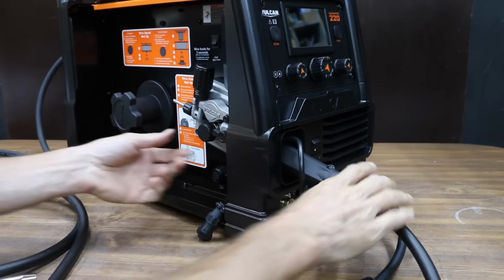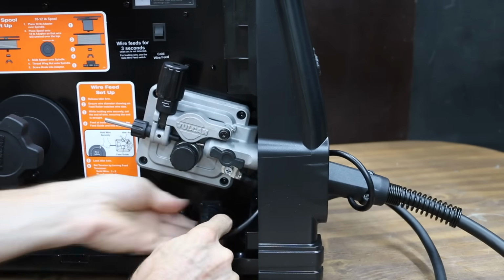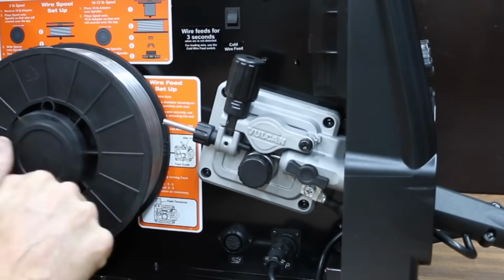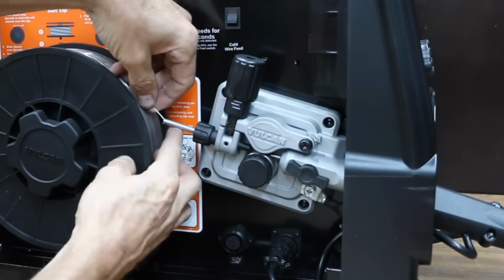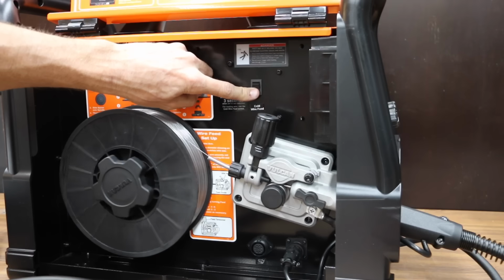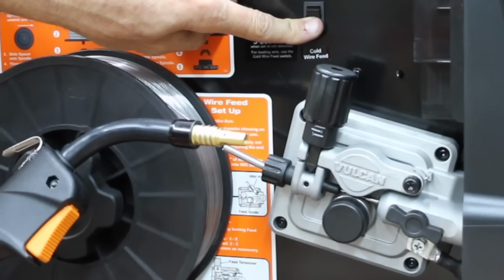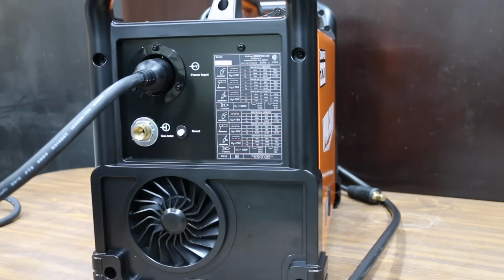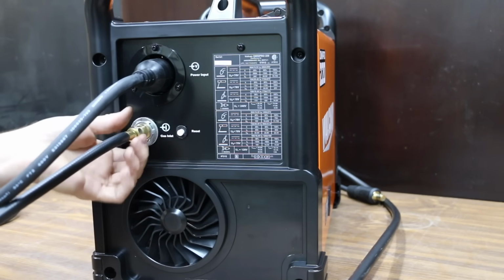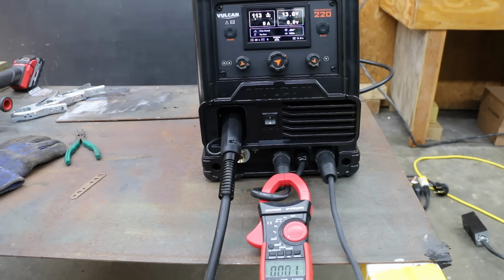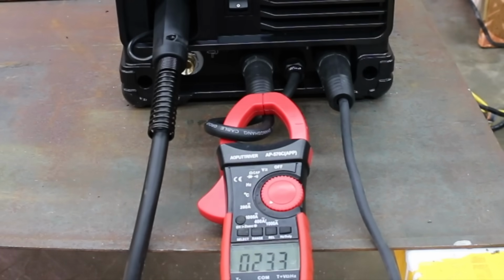Of all the welders so far, the Vulcan is by far the easiest for installing a roll of wire. However, it is a pretty large welder. The geometry for the wire feed is excellent and allows for a pretty straight wire run into the wire feed mechanism. There's a wire feed button to make the process even easier, and the gas supply hose has a threaded fitting. And with 10 pounds of wire, the Vulcan weighs 66.5 pounds. On the lowest setting, 72 to 105 amps. On the highest setting, 257 amps starting off and dropping to 206 amps after 3 seconds.